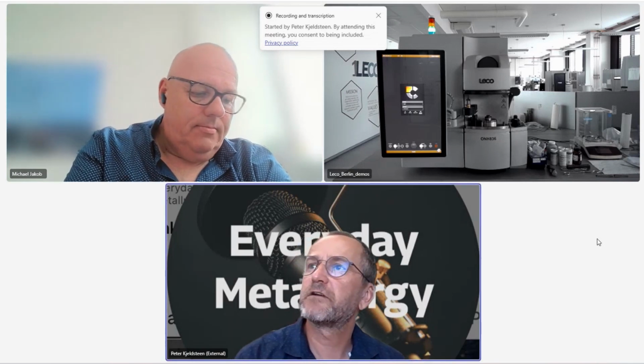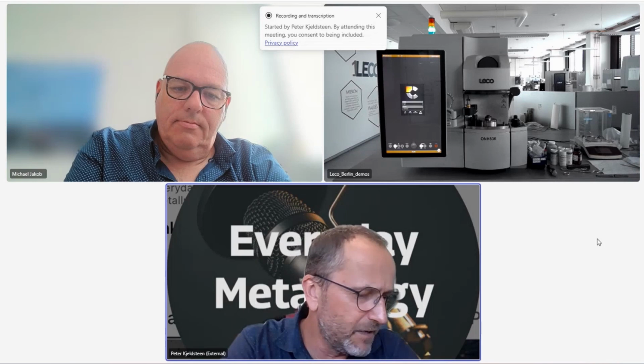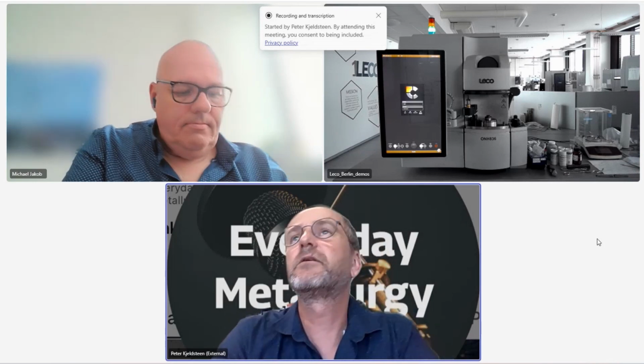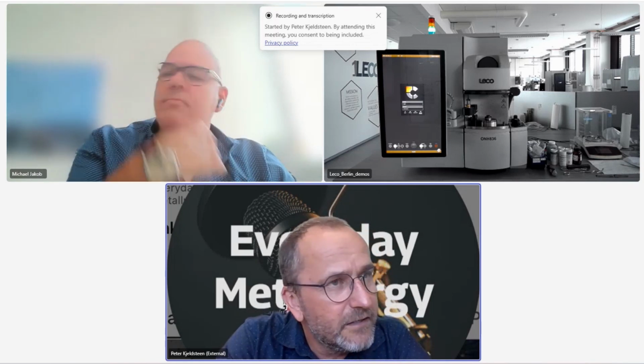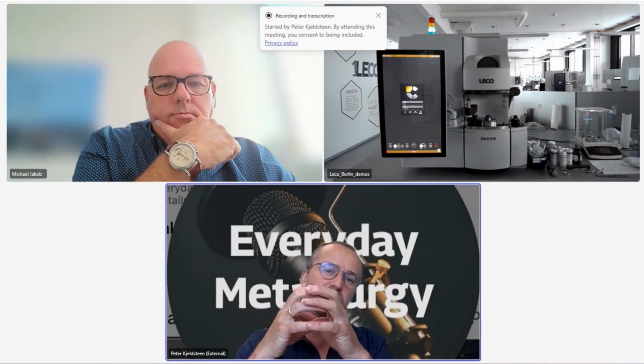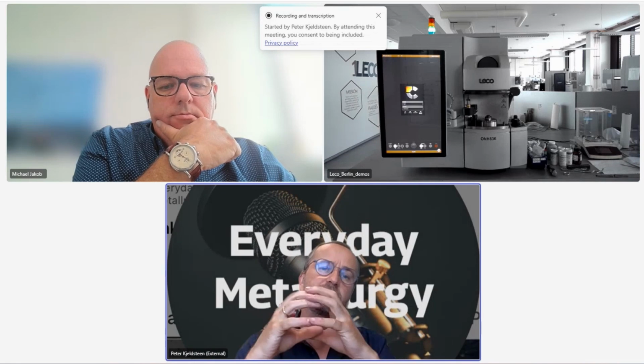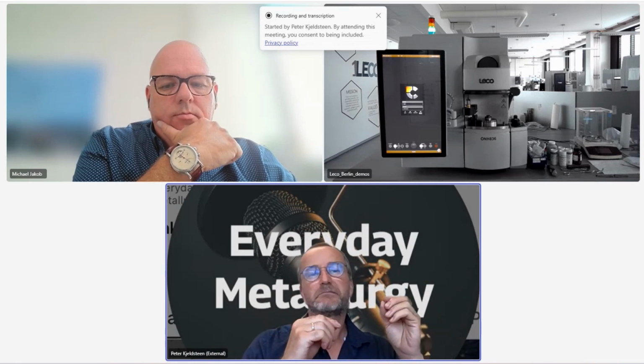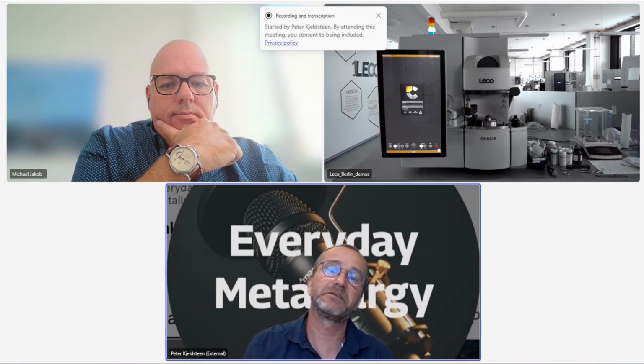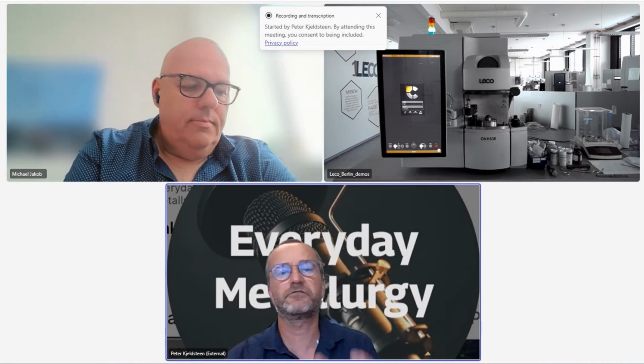I remember I was measuring some extremely special alloys, tool steel with a high amount of vanadium, and when measuring that on a standard Spark OES, I did get different results as a function of the carbide size. So in the core of the product I made, I had coarser carbide than I did at the surface. But the chemical composition should be the same, but the measurement could vary. Instead of 9%, it was 8.5 or 9.2. So I had quite a big variation.